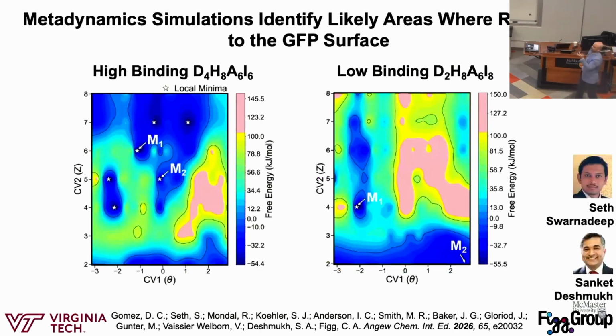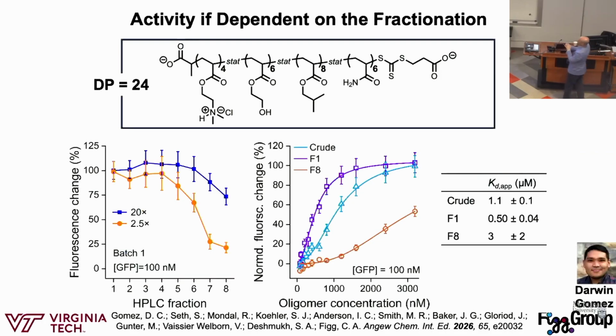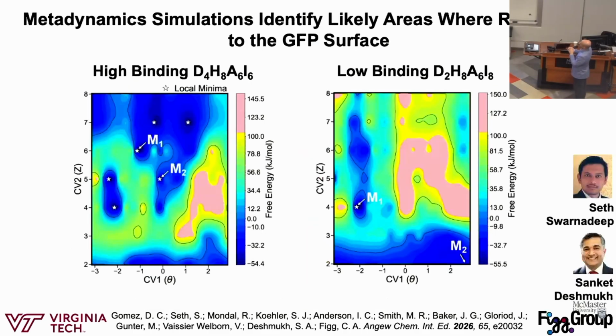The next thing that we did is, okay, we can isolate this composition, but what's actually happening in the binding? How are these oligomers actually interacting with the protein surface? That's really hard to characterize. So what we did is we took a composition from the strong binder and a composition from the weak binder, randomly generated sequences, and ran computational analysis on them. This is from my colleague Sanket and his postdoc Seth.